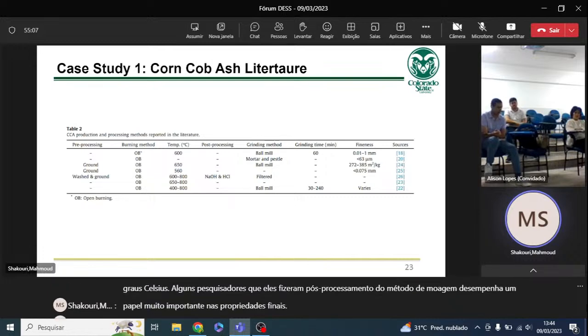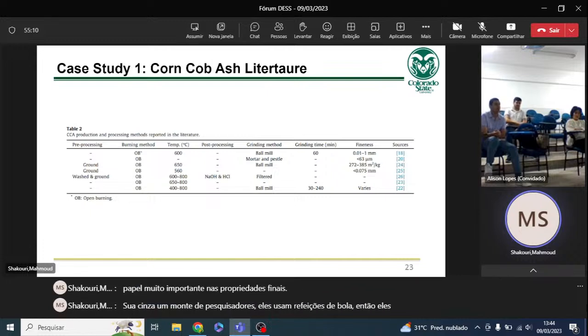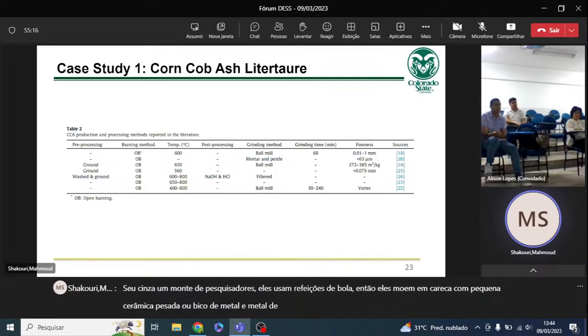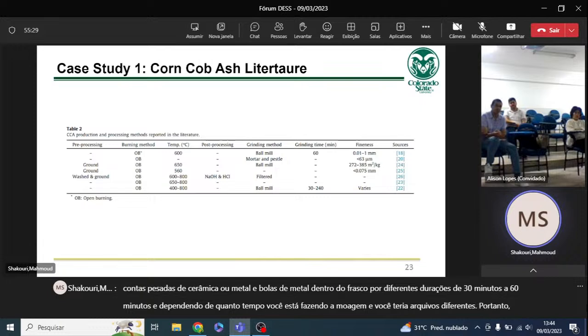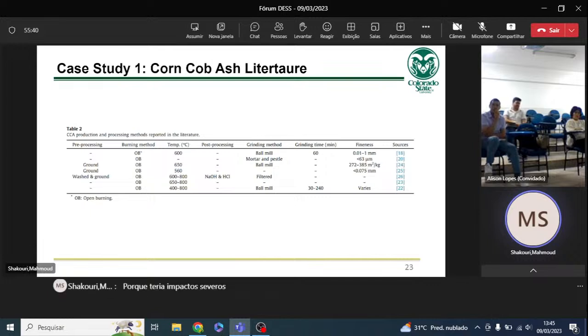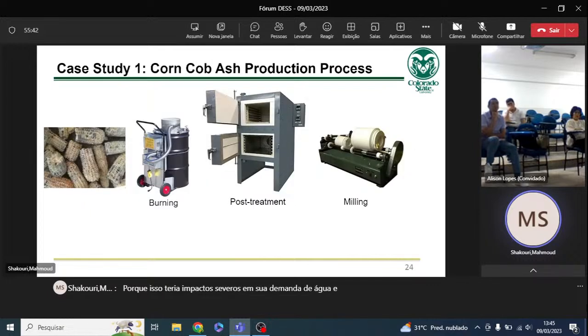A lot of researchers use a ball mill, so they mill it with small, heavy ceramic or metal balls inside a jar for different durations from 30 minutes to 60 minutes. And depending on how long you're doing the grinding, you would have different fineness. So we should try to have a fineness that is similar to the fineness of cement. You don't want to go too low because it would have severe impacts on your water demand and workability. So what we did was basically we got some corn cobs from the farms.